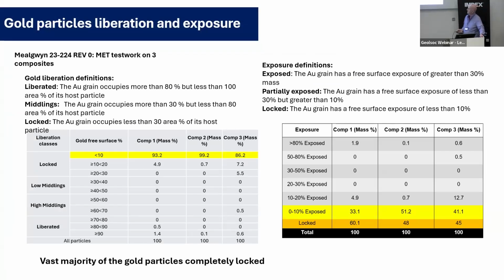Also, the locked surface of the gold particles and telluride particles is extremely important. If you look at over here, free surface, it's less than 10%. And you've got middlings and high middlings and then liberated. This is an extremely important test. If you're looking at this line here and this line here, it tells you some fairly interesting stories very, very early on. So this can be done from first pass drilling. This can be determined. Whether you're going to spend another $40 or $50 million drilling, you really should know this information before you start writing the checks.